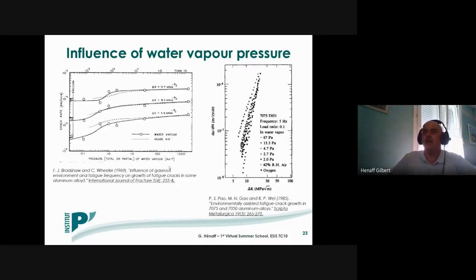But if we come back to the influence of water vapor, here are some results from literature by Bradshaw, Wheeler, or Pao and Wei, for instance. What you can see is that indeed, when you compare the fatigue crack growth rates obtained in air and then increase the water vapor pressure, you have a slight increase in the fatigue crack growth rates, which at high water vapor pressures are comparable to the one obtained in ambient air. Again, confirming the prevailing role of water vapor even in ambient air.